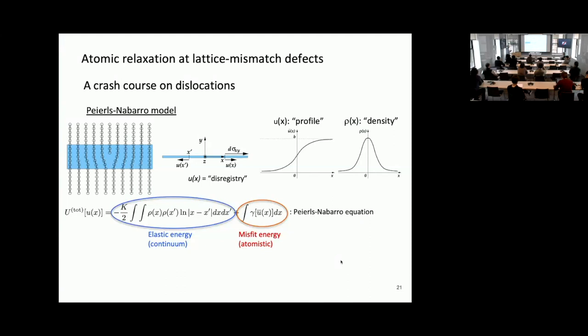In a dislocation in a crystal, you have an extra plane of atoms on the upper half relative to the bottom half. But of course, the system does not relax by matching all these layers and expelling this kind of defect all the way to the edge. It relaxes by a slight deformation around the dislocation, and this is exactly what this relaxation does. So this is what is called a dislocation. There's another reason why I'm bringing this into the picture.